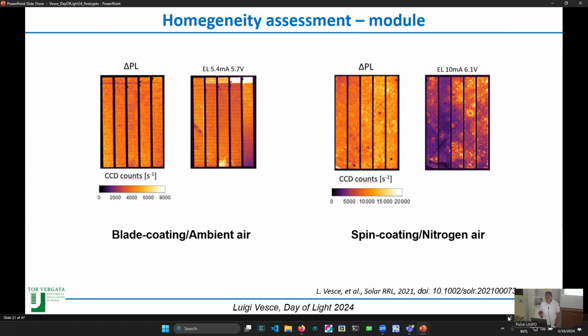About the PL, we start to have some differences. You can see some dark spots here, not so many, but here, yes. So you can see some dark spots in the spin coating case. Here you can see that the charge extraction is not uniform between the different cells, and in the blade coating case it is much better. About the electroluminescence, which is maybe the most important characterization, you can see how all the cells are different in the spin coating case, and how they are quite similar in the case of the blade coating.